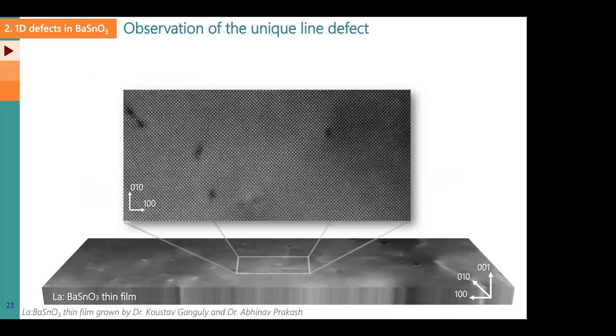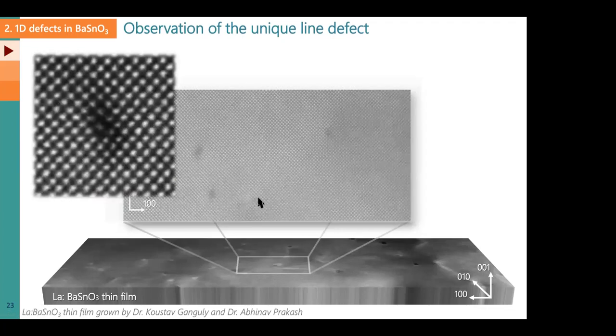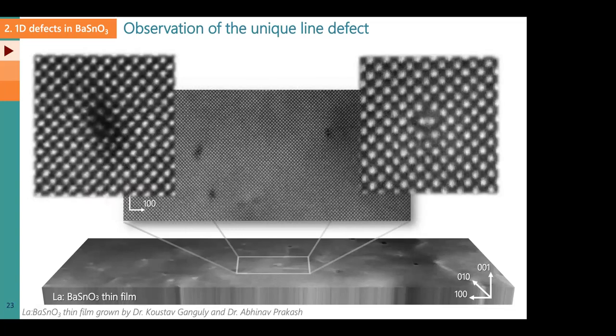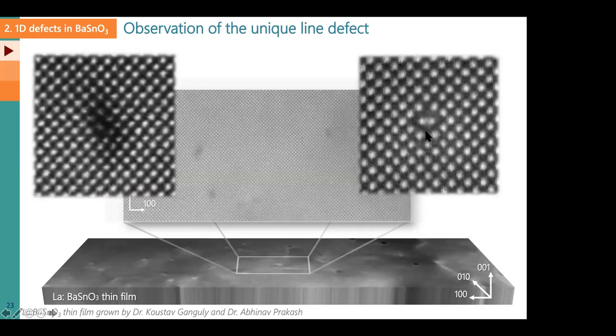In the case of barium stannate, we actually stumbled on a defect that is indeed metallic. Here's how it looked. Here's another image from barium stannate. You can see a couple of line defects right away. This one is actually a dislocation, and this one is the new one. How do I know it's a new one? It looks different. If I take this one and make a loop around it, that's a classic dislocation, where the loop doesn't close, as should be the case for every dislocation. In this case, I make a loop and it completely closes. That's odd, unusual, but at the same time very promising. You can see the structure in the middle is different, so we are on to something.